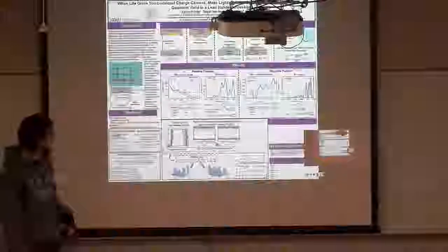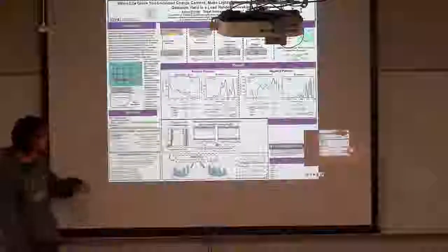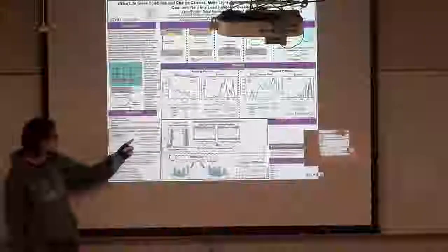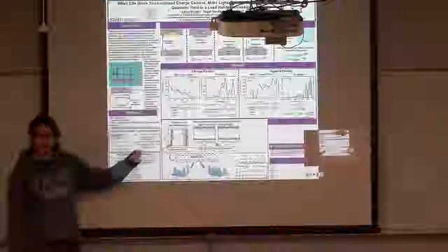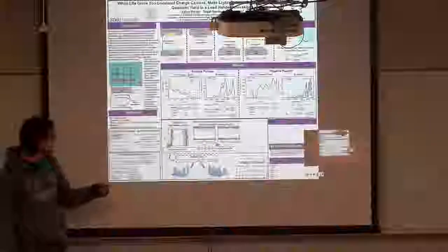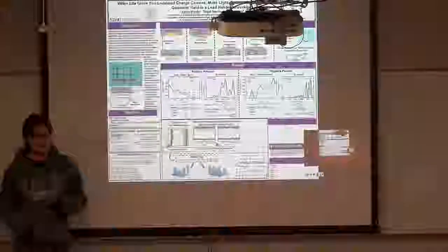And they have a bunch of, I guess I'm just going to have to work on describing the couplings and the parameters in them a little bit better, but we don't have to go too in depth into them because we're going to approximate them using Kohn-Sham DFT. So we assume that for our electronic and nuclear energies, we can just use the adiabatic states for our ground state method, and then to approximate the polaron formation, we add an additional charge and let the model optimize around that charge.